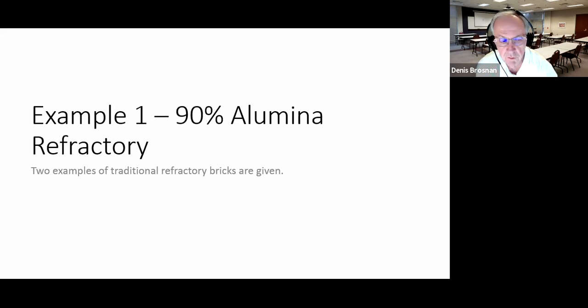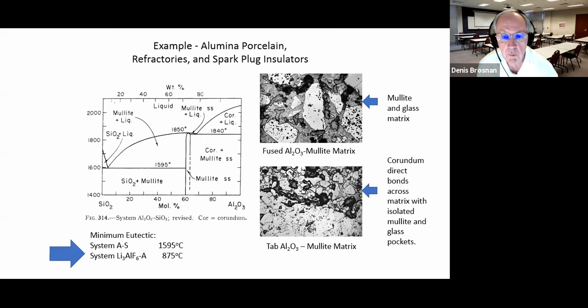Okay, well, I tried to convince you that a lot of things can happen prior to forming the shape. But now we're going through a drying process as we may find necessary. And we're going to make a 90% alumina refractory. Okay, now I'm going to talk a little bit about older technology. Okay, and in the refractory products, when you look at the microstructure, you can make that two ways. You can make the product with fused alumina aggregate with a lot of matrix containing mullite around it. This matrix and product was formed using some tabular and calcined alumina along with silica sources, but the main thing is the fused alumina in the matrix.